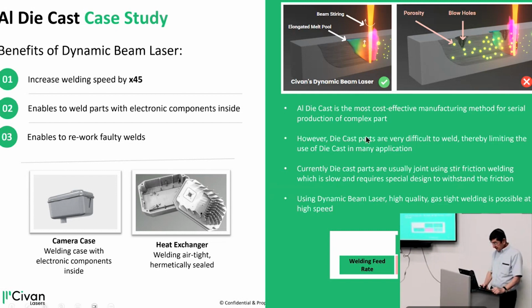And again, the way they do it today, at least these customers, is with friction stir welding. The speed that they're doing today for this product is 0.2 meters per minute. We're doing it at 9 meters per minute. So it's 45 times faster, okay? Not 20% faster. It's a factor of 45. That's the difference between the technologies.